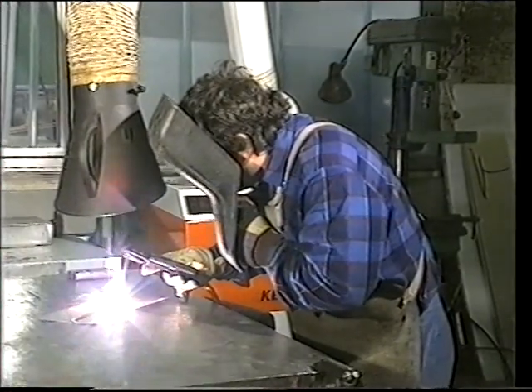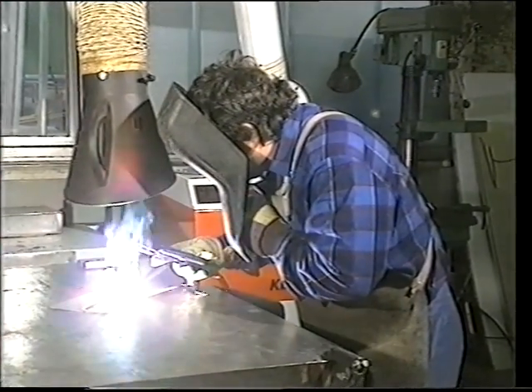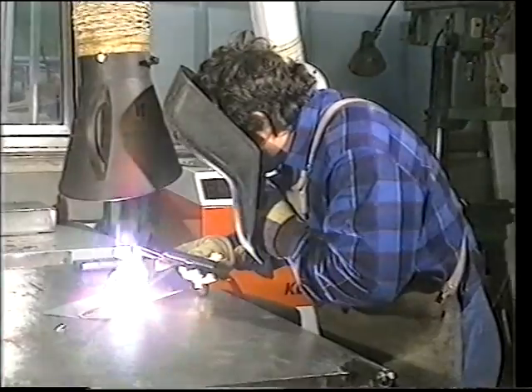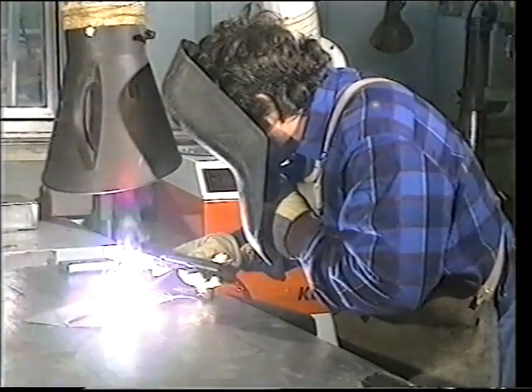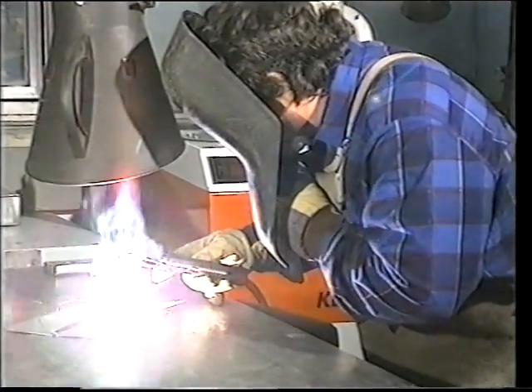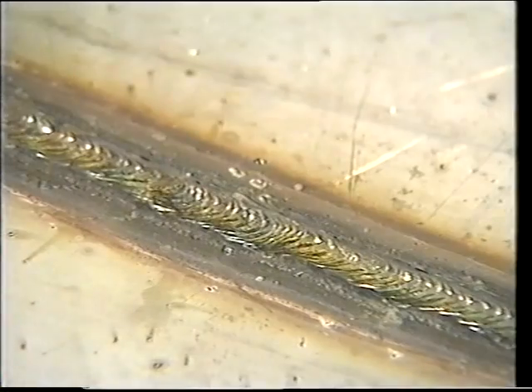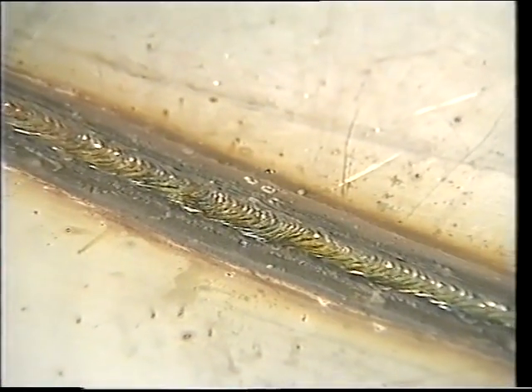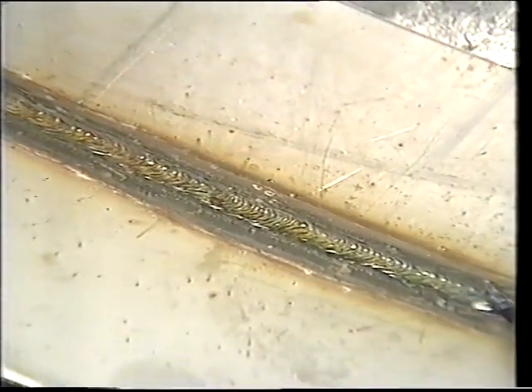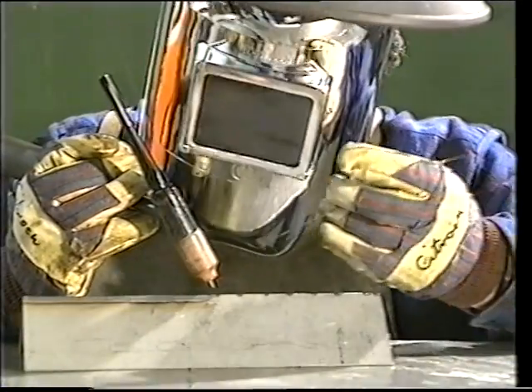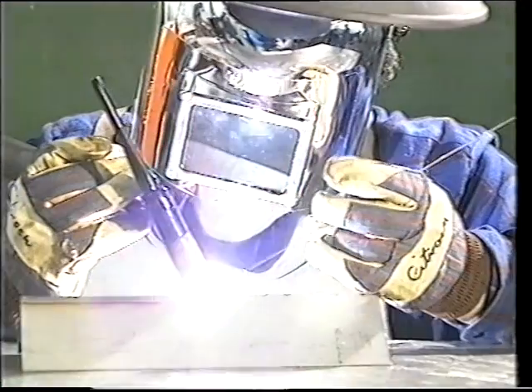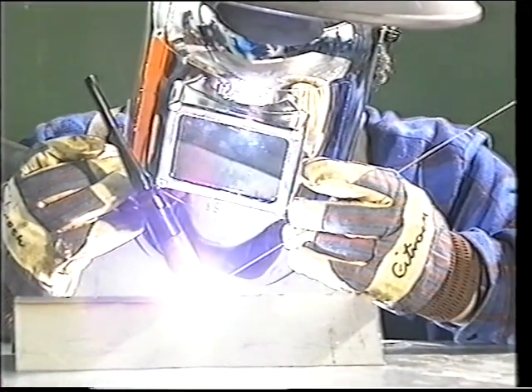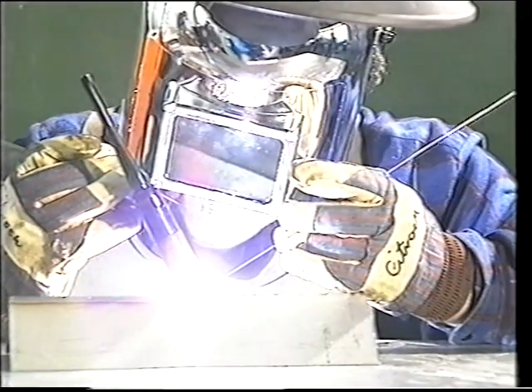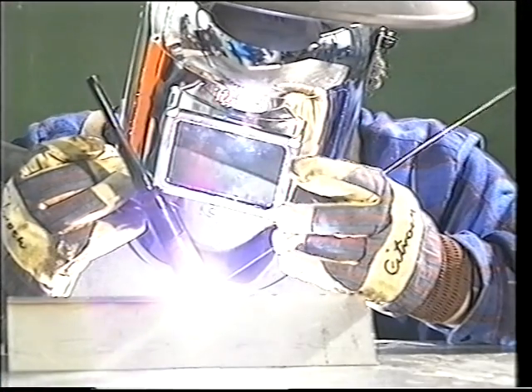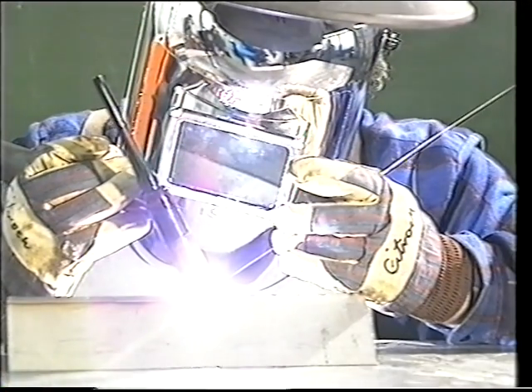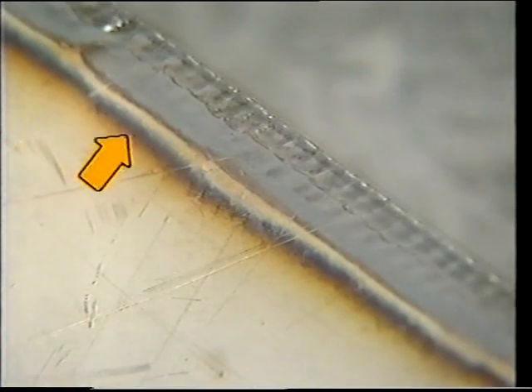Welding also removes the passive layer. The oxides produced during welding cause potential differences which promote the electrochemical process of corrosion. Complete removal of these oxides after welding is the only way to prevent this. Stainless steel is usually welded with the tungsten inert gas or TIG process. Even the very thin oxide films generated by this method can lead to corrosion. They must therefore be carefully and completely removed. But how?